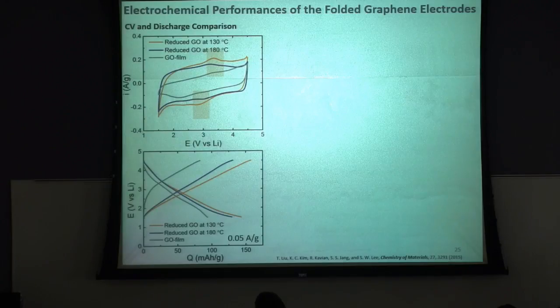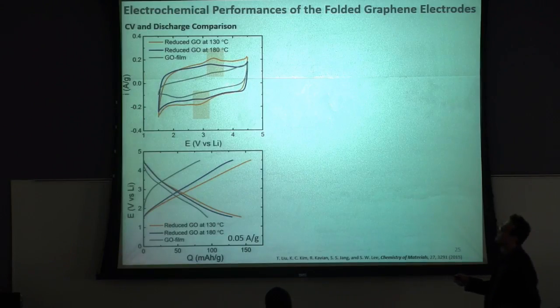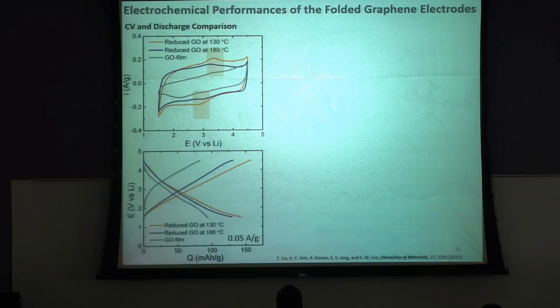If we measure the charge-discharge performance of these graphene electrodes, this gray one is the graphene oxide film. If we reduce at 130 or 180 Celsius, you can see the development of oxidation and reduction peaks. Interestingly, if we increase the temperature too much, we see a decrease of this redox peak. This is because if we increase the reduction temperature too much, we are also removing some active redox functional groups, right? That means there is some optimum reduction temperature. You can see this reduced graphene oxide film has good capacity, around 140 to 150, after reduction at 130 Celsius.